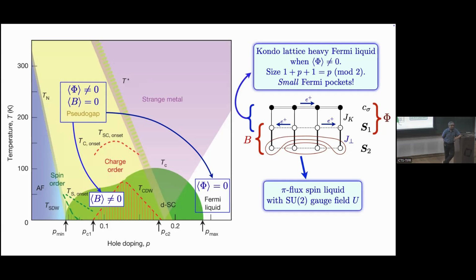So the D wave is also a prediction of that particular spin liquid. That's not a new statement. People had talked about that already in the 90s. But what we get in addition is that the velocities of the nodal quasiparticles in the two directions are very, very different. That was not the case. That was a big problem in the early days.